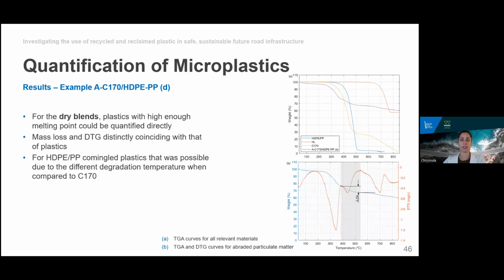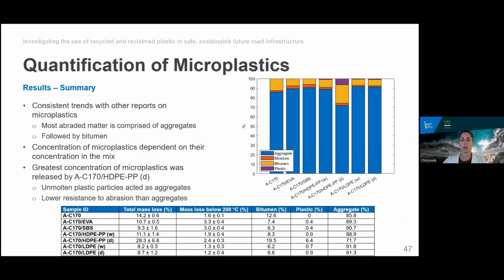So for the dry blend of HDPE and polypropylene, which did not soften during the mixing process, we were able to measure the concentration of plastics directly, as you can see in the figures to the right here. So overall, most of the abraded matter was found to comprise aggregates, followed by bitumen. The concentration of microplastic was found to be dependent on their concentration in the blend, and so the blends modified with LDPE and HDPE polypropylene were found to release more microplastics. However, we need to note that their concentration in the blend was 10%, which was greater than that of the SBS and EVA in the respective blends.